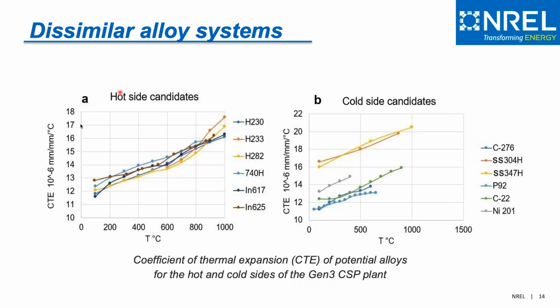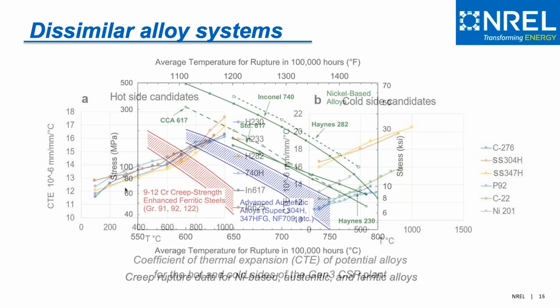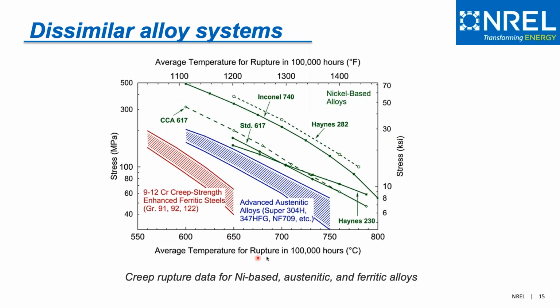So here are some of the hot candidates. Hot candidates for me are for 720 degrees C, and the cold side candidates are for 500 degrees C. So for this one, I'm considering what are the properties of those alloys that I can use based on the CTE. And if I'm combining this one with this one, I'll try to match the CTE, that is the coefficient of thermal expansion. In this case, I'm showing you the rupture in a range of